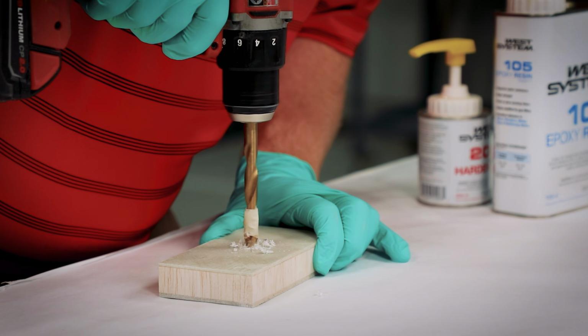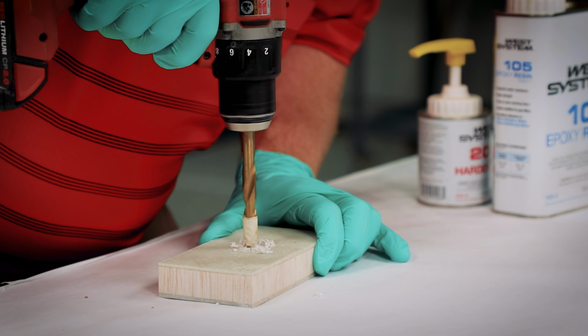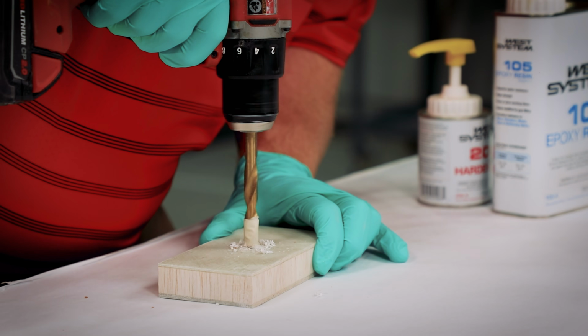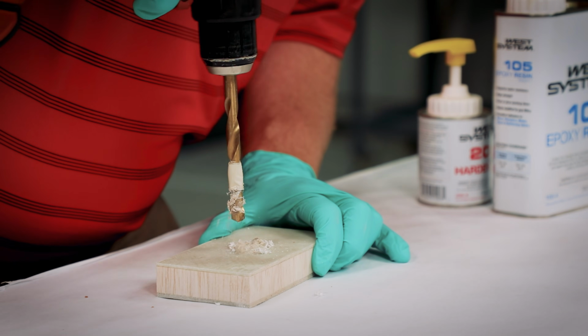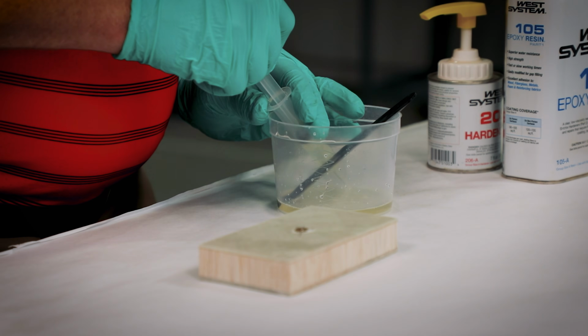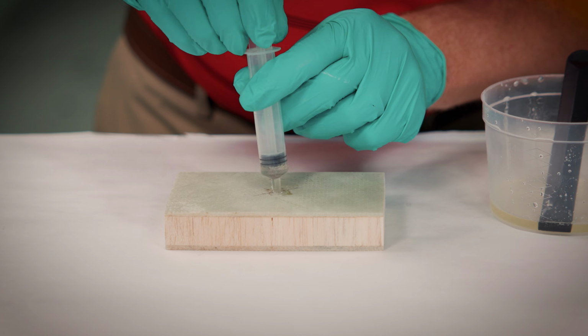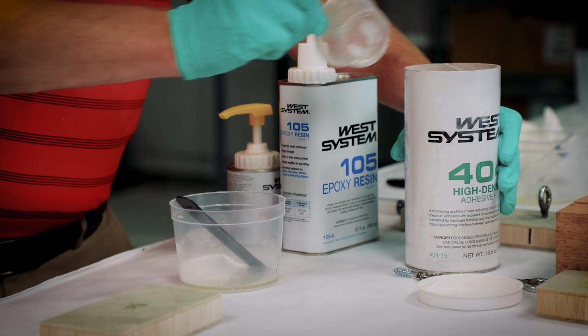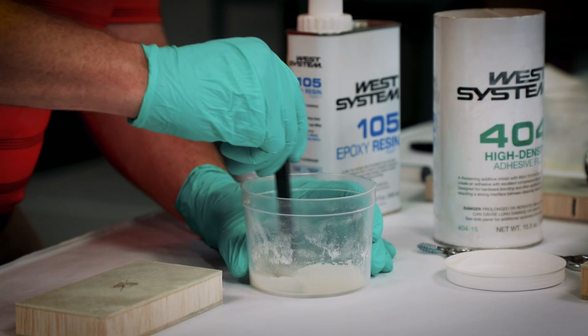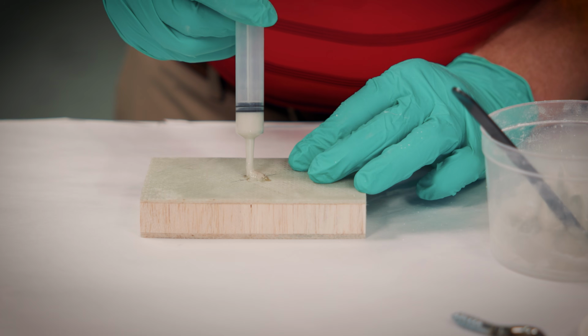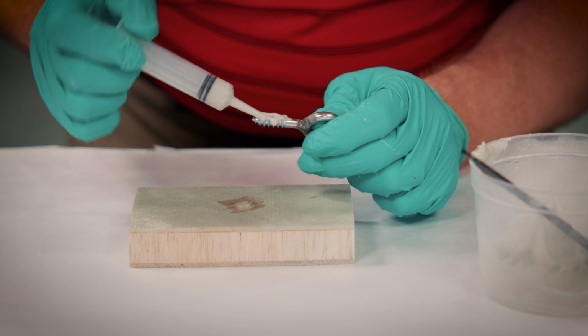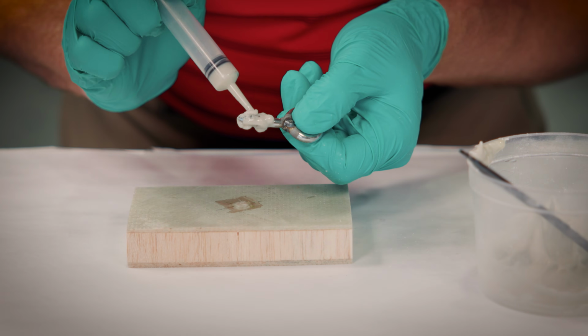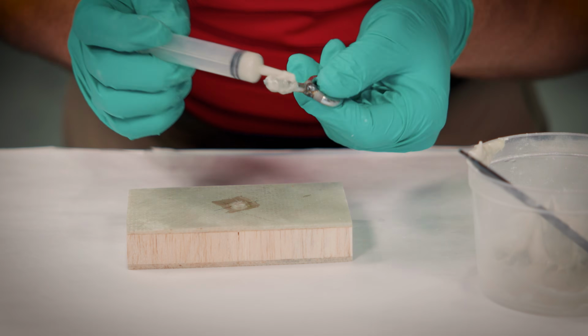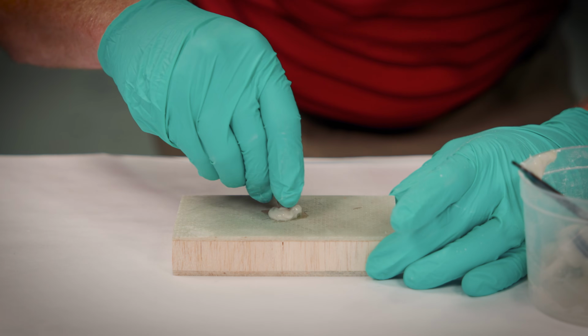Block number 3, I'm going to oversize the hole 50%, which is a 3/8 of an inch diameter drill bit, and I'm going to drill down 3/4 of an inch deep. Then I'll fill that with a 105-206 mixture and fill it completely and let it soak in for 5 minutes. Then remove the excess and backfill it with the 105-206 and 404 high density filler to a non-sag consistency. Again, you could use the 406 colloidal silica filler as an option.